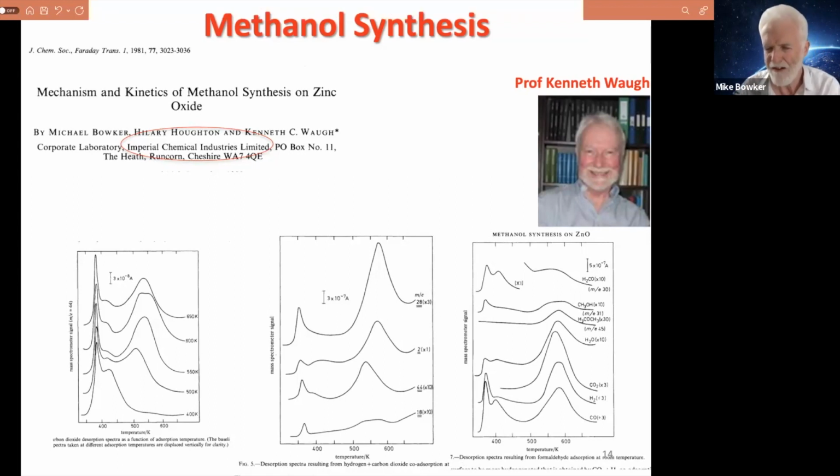So at about 580 K or so, you see a whole slew of products evolve: CO2, hydrogen, water, a little bit of dimethyl ether. You can see that signal is multiplied by 30. Methanol is multiplied by 10. And that coincident desorption of all those products is an indication that there is a common intermediate which is responsible for all of them.